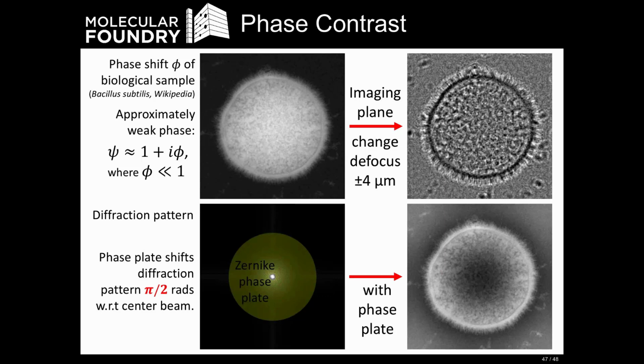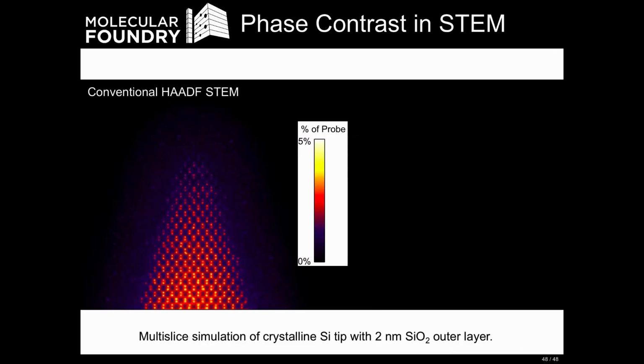Okay, so why do we care about phase contrast? We can form beautiful atomic resolution images. This is a multi-slice simulation here of a crystalline silicon tip with a 2 nanometer outer shell of silicon dioxide. And the image is quite sharp, quite clear. You can see a little bit of contrast in the amorphous region and quite a bit of contrast in the zone axis aligned silicon columns here in the center. And silicon's not a particularly heavy atom, but we can still see a pretty big amount of contrast.